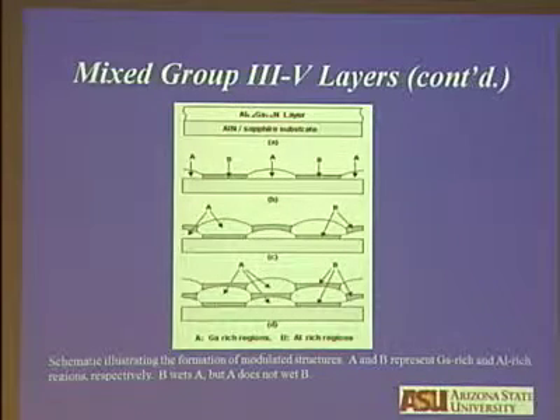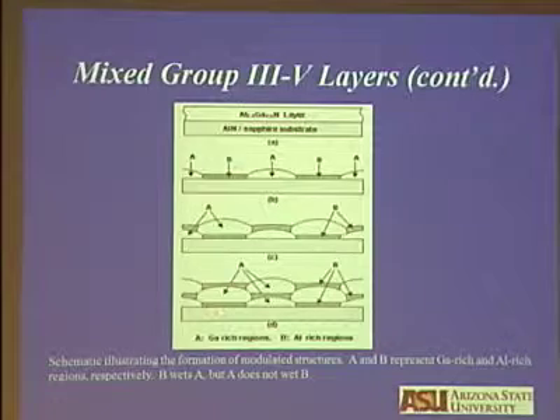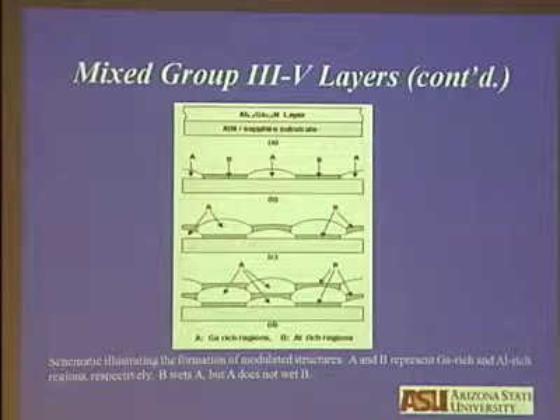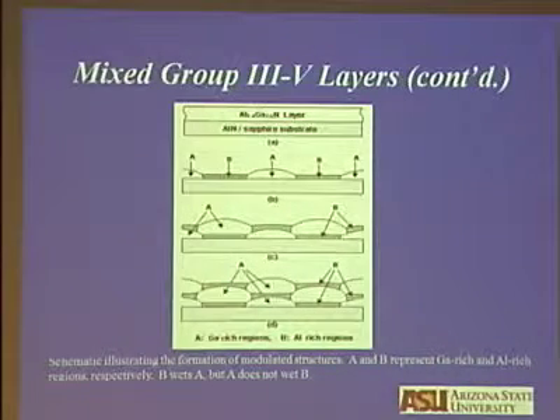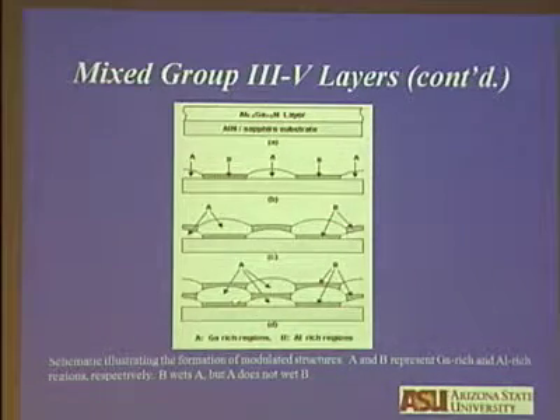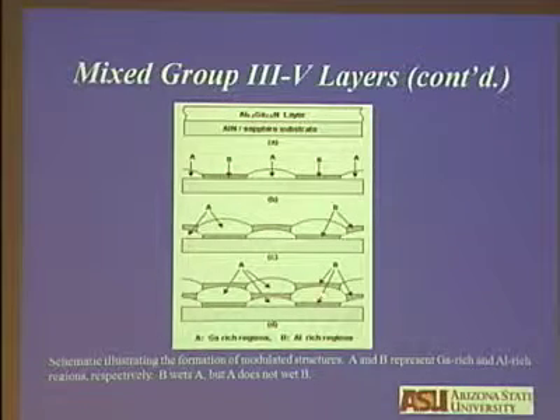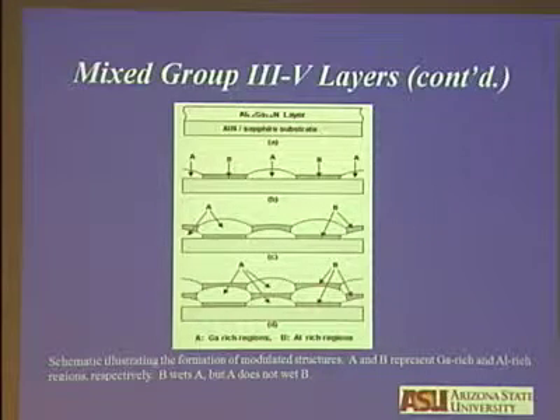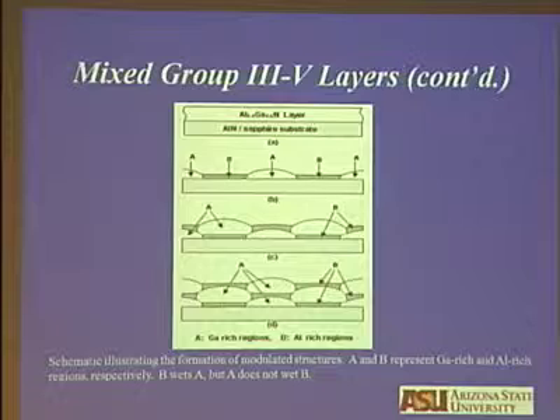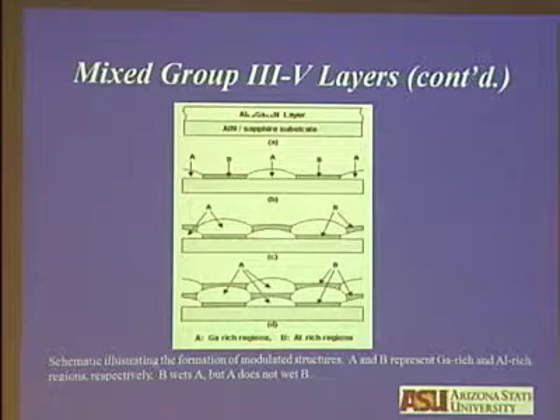A on B or B on A, and you see this wets this one, you get this structure, and you start growing. And when you remove the interface between A-rich regions, this dashed line here, you can explain the evolution of the structure. I can change the modulations here by changing my growth conditions and composition, and then you can see the extent of the aluminum-rich regions and the gallium-rich regions in the modulated structure. We have not measured the electronic properties along the growth direction and normal to the growth direction. That's a challenging problem to have.